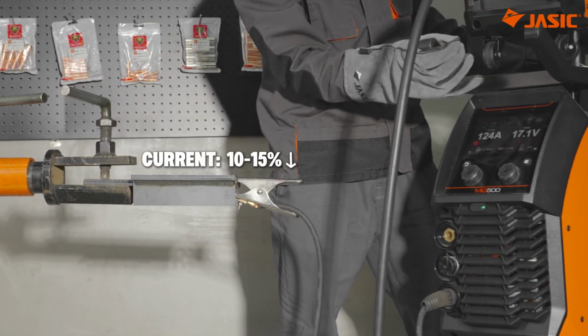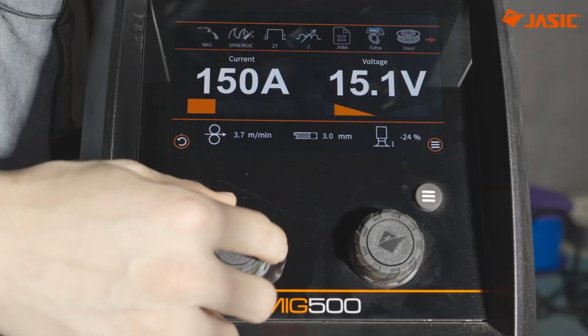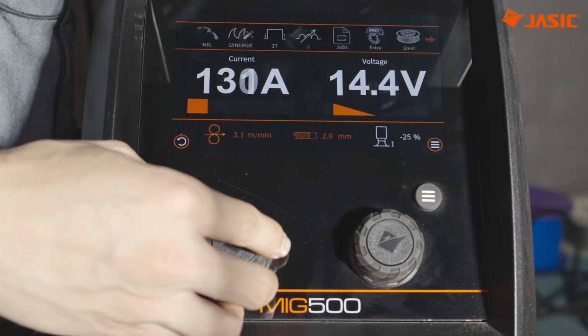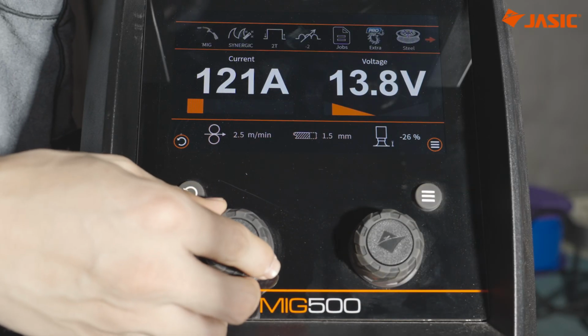Set the current around 10 to 15% lower than you would use for a fillet weld in the flat position. Too much current means too much heat input, making the molten pool more likely to sag. A typical starting point for gas flow is around 15 to 20 liters per minute.